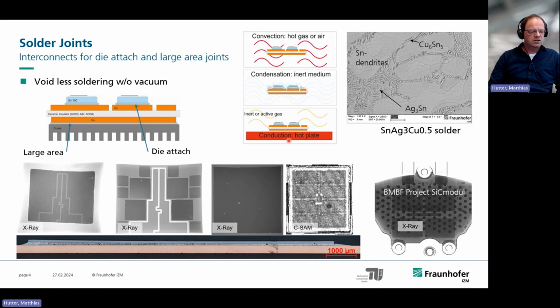The special thing is if you use conduction soldering, and you don't use any form of liquid flux which can evaporate and be entrapped, you might be able to circumvent the usage of vacuum, but in most cases, vacuum is part of the process in order to get rid of the pores and at the end achieve an almost voidless solder interconnect. Here you can see a microstructure of a tin silver copper solder. For power electronics, there's also the usage of tin silver copper antimony solder, for example, in order to have a higher strength and a higher melting temperature, so that the lifetime can be a little bit increased.